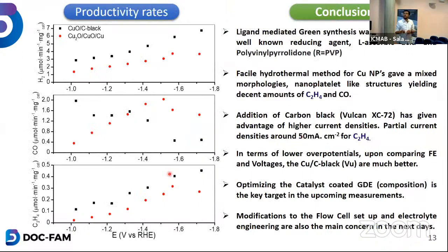And then when we look at the productivity rates, of course for hydrogen, what is the advantage of having only copper oxide with carbon black, or only the metallic copper with carbon black, and only the copper particles? Here the productivity rate for the carbon black is very high for ethylene, very high for hydrogen, and we have to take care of this by doing some electrode engineering, like by having some hydrophobic effects to minimize the electrolyte passing through it, and to have a smaller number of protons available to form hydrogen.